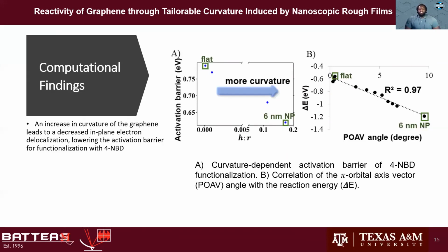And so moving on to the computational side of this project, we use molecular dynamics. Using molecular dynamics, curvatures at and between our experimental cases were created to understand the structure-activity relationship. Now, density functional theory was used to calculate the energetics of these structures and curvatures in between to understand the reaction energetics between 4-NBD and varying curved graphene.